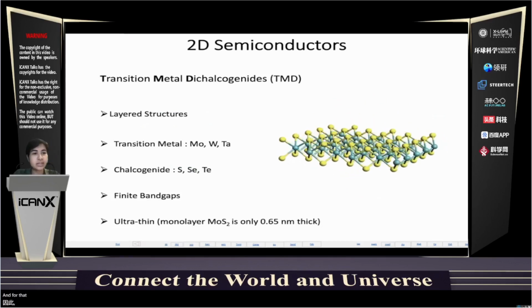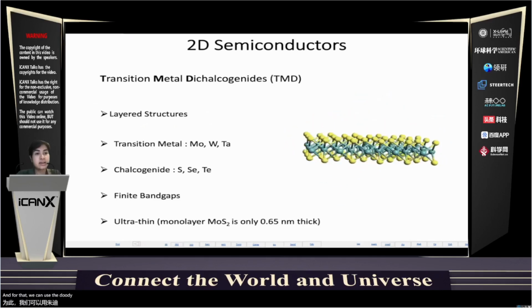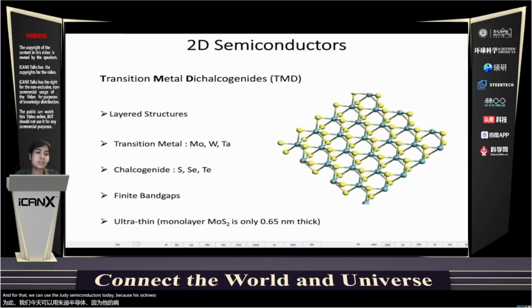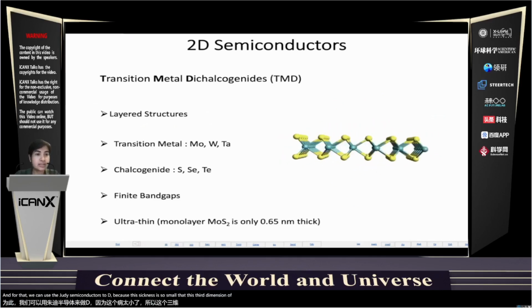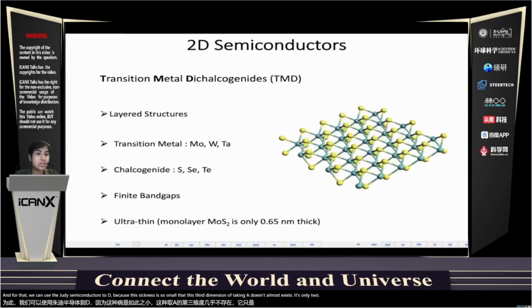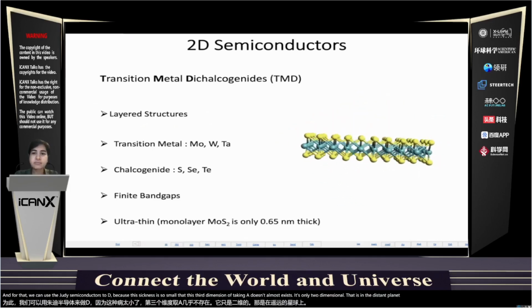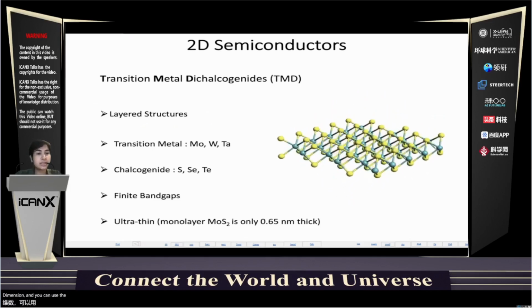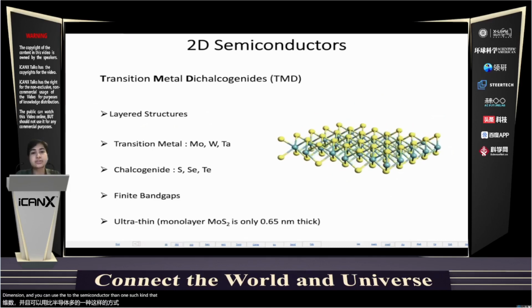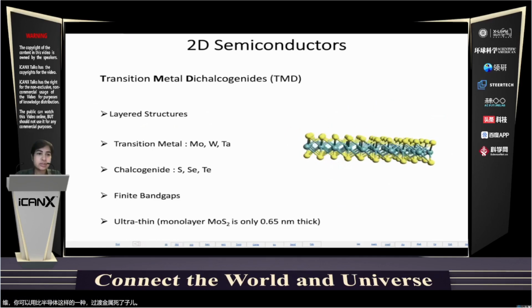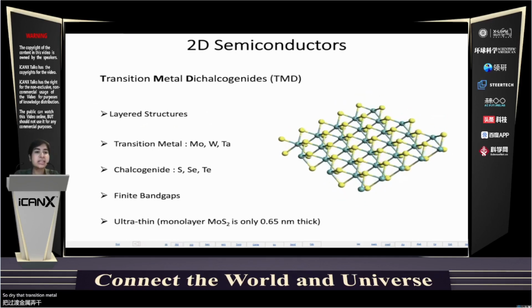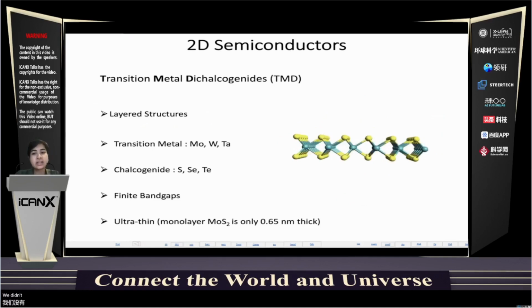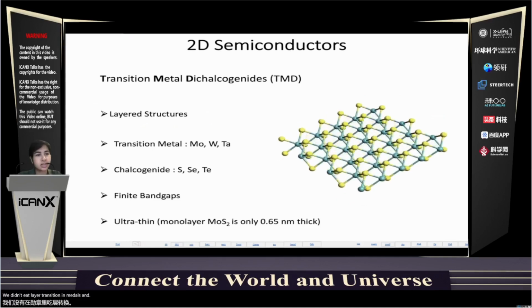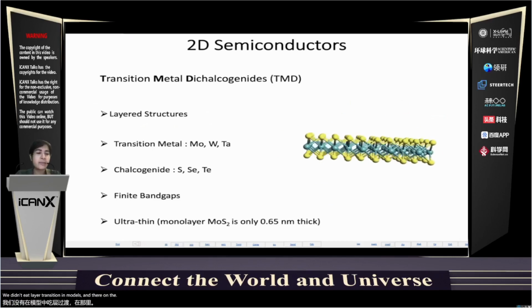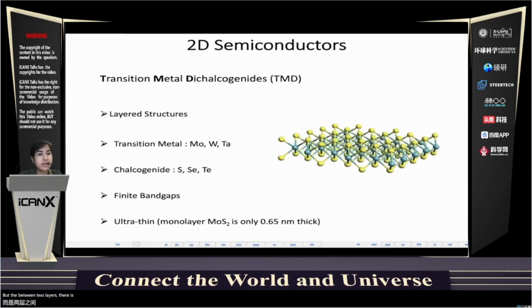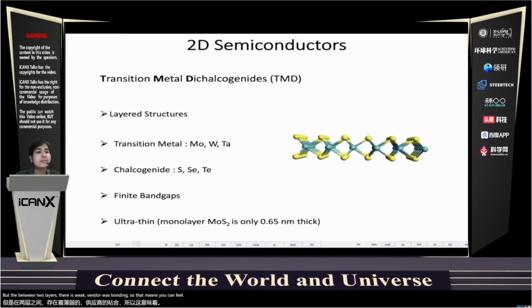And for that, we can use 2D semiconductors. 2D because its thickness is so small that this third dimension of thickness almost doesn't exist. It's only two-dimensional, that is just in planar dimension. You can use 2D semiconductors, and one such kind is transition metal dichalcogenide. So transition metal dichalcogenides are actually layered structures. Within each layer, transition metals and chalcogenides are bonded covalently, but between two layers, there is weak van der Waals bonding. So that means you can peel them off layer by layer.